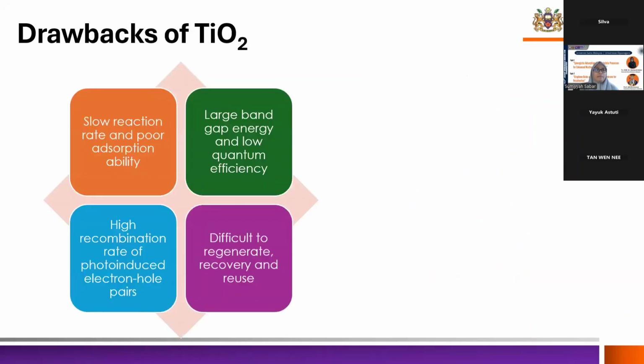However, there are a few drawbacks of using titanium dioxide alone. It has low reaction rate and poor adsorption ability. So when you have a poor adsorption ability, it's difficult to attract the pollutant to the surface of the photocatalyst. It has large band gap energy and low quantum efficiency. It has a band gap energy of 3.2 electron volt. So this makes it only active under ultraviolet radiation.